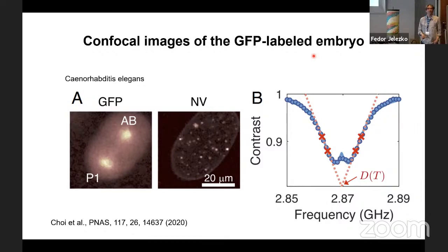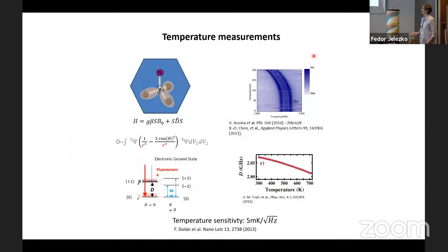Now it is true that optical readout can affect, so can basically heat the nanodiamonds. So there are two ways. There is a fundamental limit of heating: every time an NV center absorbs a photon, it emits mostly in the phonon sideband. And there is a difference of 0.3 eV or so, so that's what you dissipate in the lattice. That's hard to overcome with an NV center. And so this is kind of an intrinsic heat source, but it's not a very big dissipator.